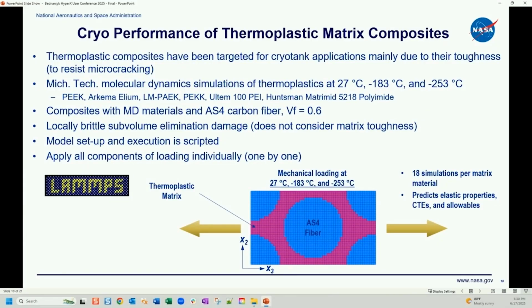Of course, for a final design, you'd do testing at the ply level and above. But so we took this, we made all the volume fractions 0.6. We used AS4 carbon fiber for all the composites. As I said, we did progressive damage to predict the allowables. It does not consider matrix toughness, so this is one place we could sharpen the pencil here. We could use a damage model in the micromechanics that takes advantage of the toughness of the matrix to give a better prediction about what will perform in cryo. But so this step, LAMMPS was used for, that's the molecular dynamics code, predicted the thermoplastic matrix properties, and then we used this micromechanics model to predict the ply level properties at these 3 temperatures.